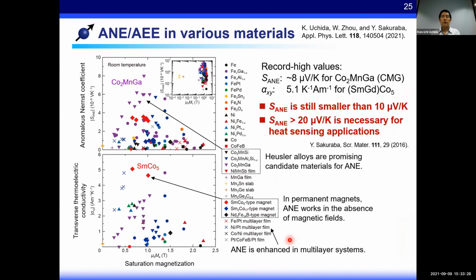Up to now, we have introduced the advantages and the unique functionalities of the anomalous Nernst and Ettingshausen effects. However, these phenomena are currently far from practical applications because the anomalous Nernst coefficient is still much smaller than the Seebeck coefficient of materials used nowadays. The current record-high value of the anomalous Nernst coefficient at room temperature is still smaller than 10 microvolt per Kelvin, while Dr. Sakuraba at NIMS estimated that at least 20 microvolt per Kelvin is necessary for heat sensing applications based on the anomalous Nernst effect.